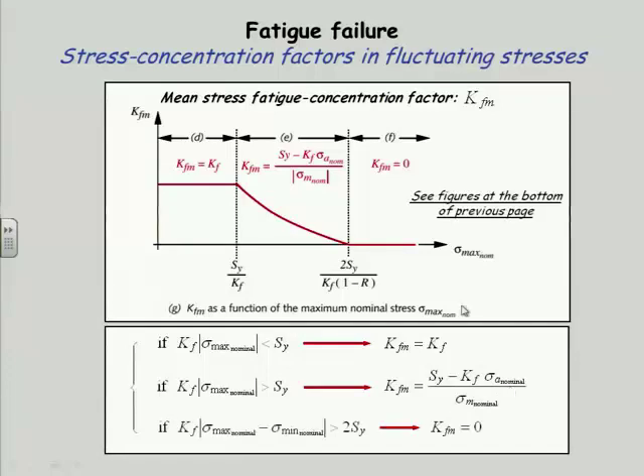So this is just a summation of what I said. So if Kf times the maximum nominal stress is less than Sy, I use the entire amount of K sub f for Kfm. If it's greater than Sy, then I have yielded locally in the notch, and I use this funny formula. And if it's greater than 2 times Sy, then I say I've clipped it on top and bottom, and my mean stress is effectively gone.